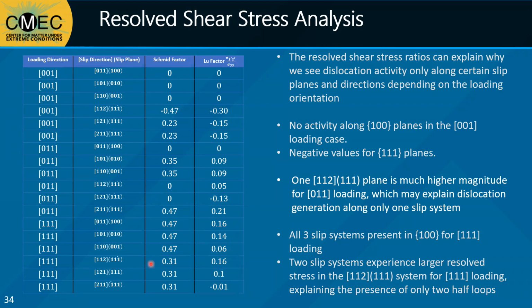And finally, for the 111 planes, we can see that two of these slip systems have positive values, and the final one is both small and negative. This could explain why we see only two half loops forming between these three rectangular bands and one that is missing.